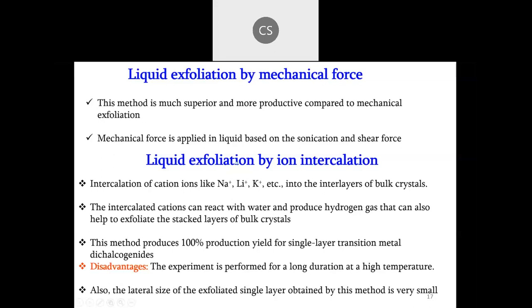In the case of liquid exfoliation by ion intercalation, which is nothing but the intercalation of ions like sodium, lithium, potassium, etc. between the interlayers of the bulk crystal, followed by applying some mechanical force, we can get very high quality powders. But the disadvantage of liquid exfoliation is that the experiment is performed for a long duration, at minimum 1 or 2 hours. Sometimes it also requires high temperature to get very pure and high quality powders. So these are some of the disadvantages.